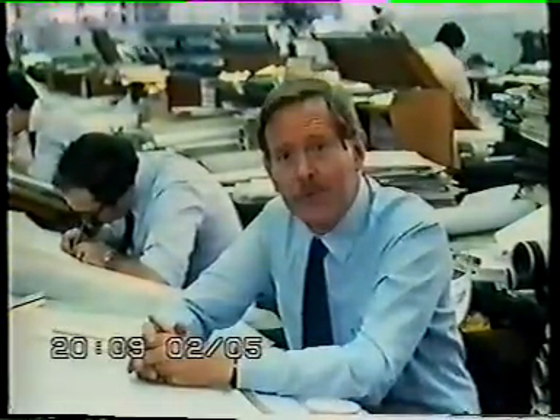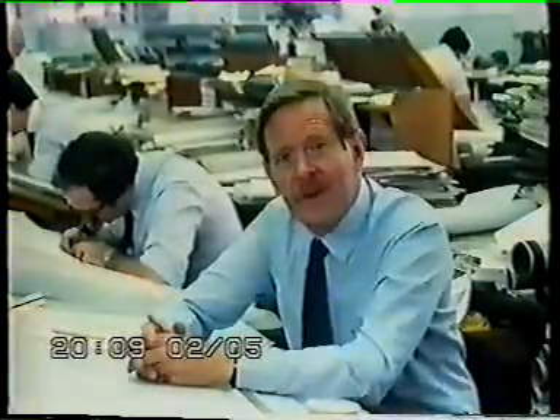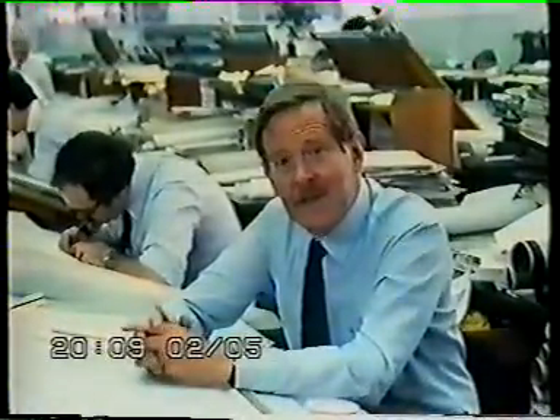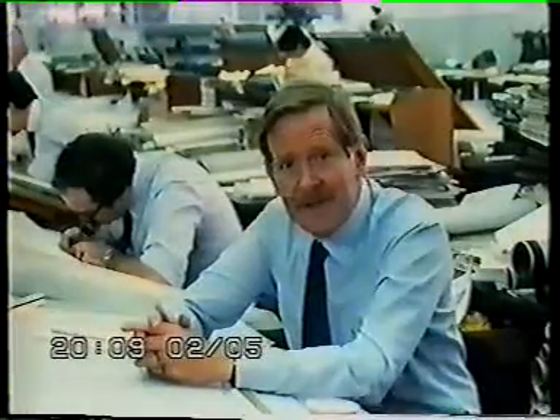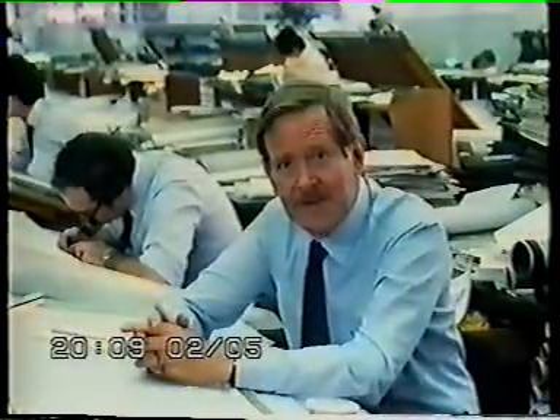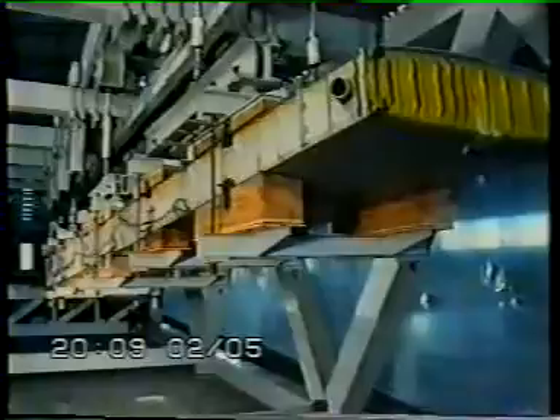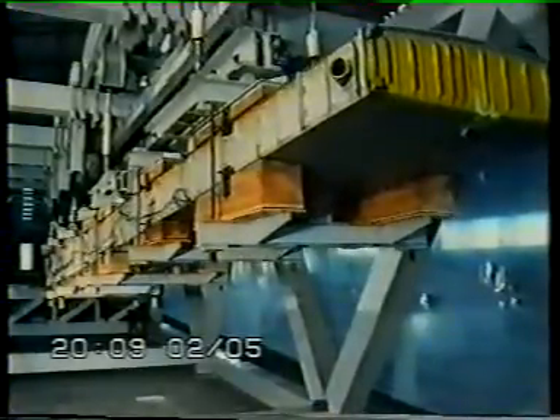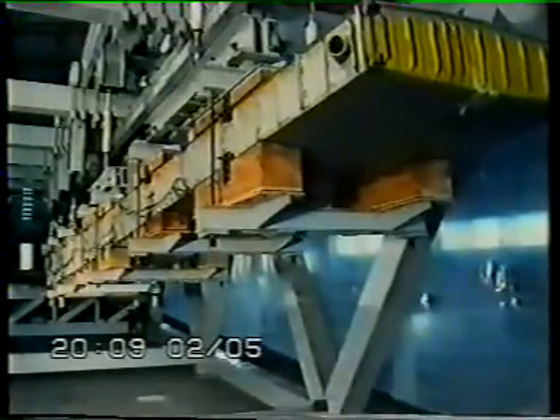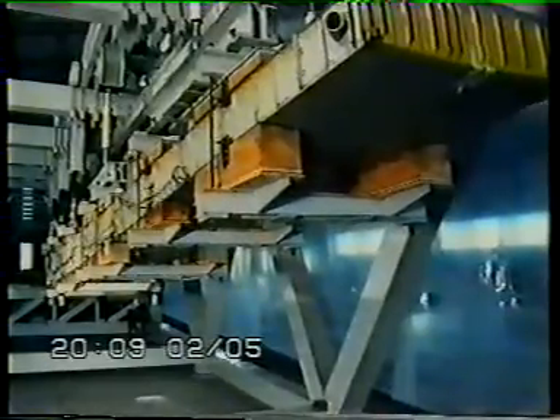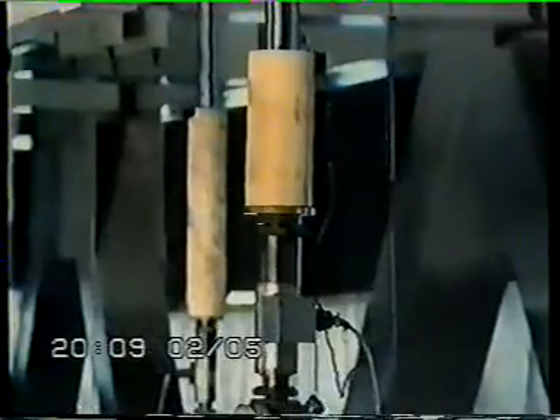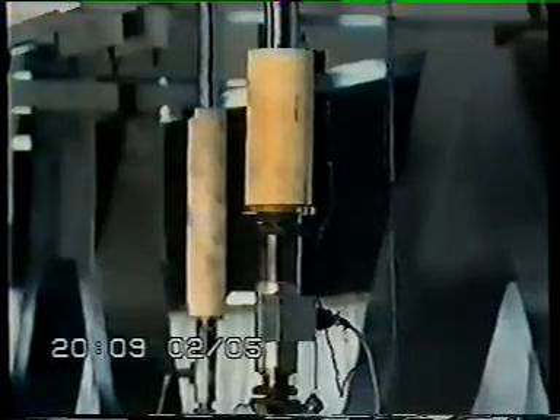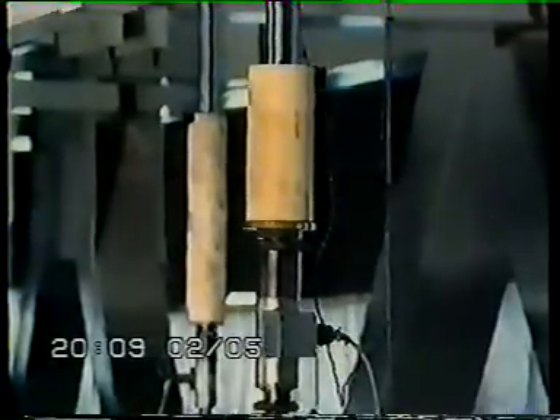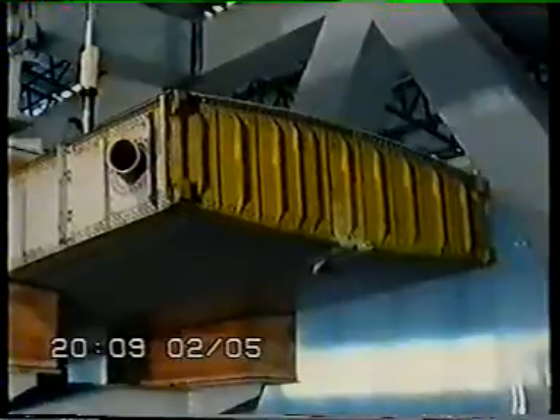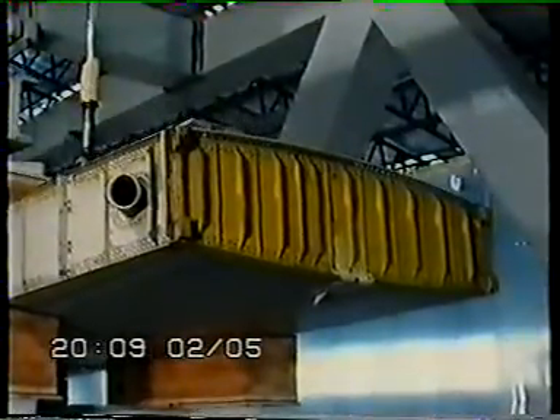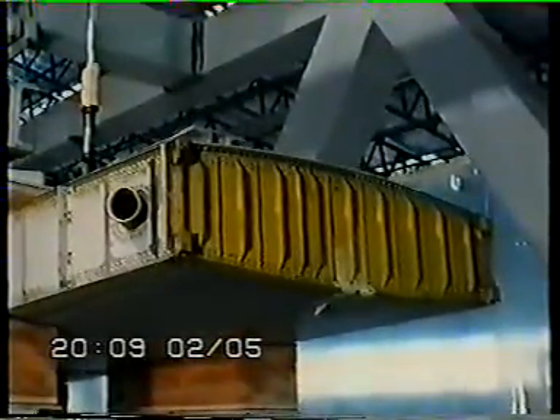An alternative philosophy used is fail-safe design. In this case, structural integrity is assured by detecting damage before it weakens the structure dangerously. Virtually all civil-type aircraft and their military derivatives, such as VC-10, TriStar, BAE 146, are so designed. The main point of fail-safe designs is that they're tolerant of quite large defects, several inches long perhaps, which grow only slowly.